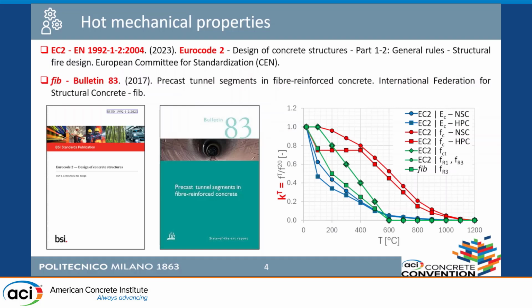So starting from what we saw in the previous speech, which was very interesting, here I start from what the standards say, mainly making reference to EC2, about the hot mechanical performances. So we are speaking about the performance of the material during heating. Here in the graph, we can see in red the curves referred to compression. This is the relative decay of the compression with temperature. We have two curves: this one refers to what I call here normal strength concrete, in the sense that the Eurocode makes reference to compressive strength lower than 70 megapascal, and then concrete with a compressive strength higher than 70 megapascal. So it does not make reference to UHPC. Maybe it's more like HPC, but anyway, we can imagine to be here.